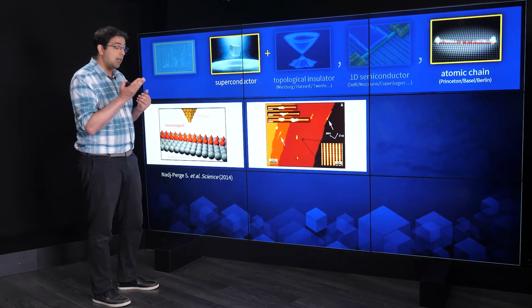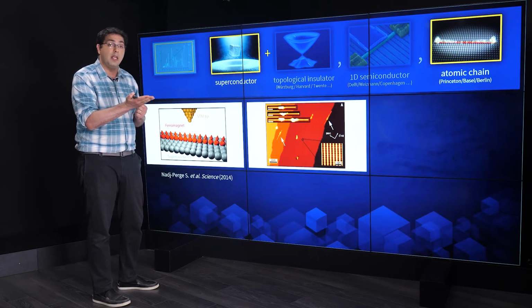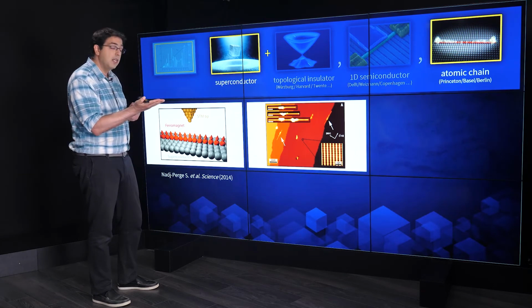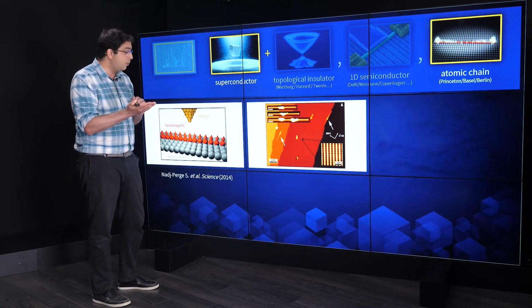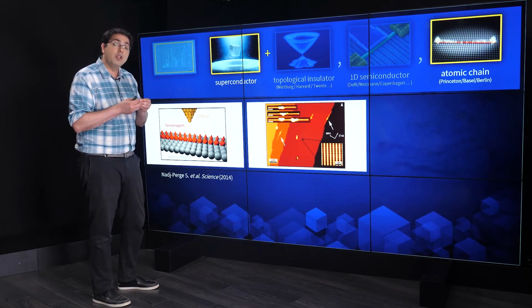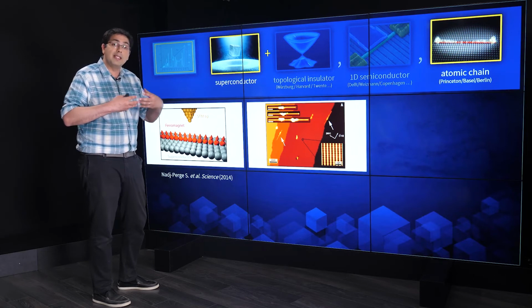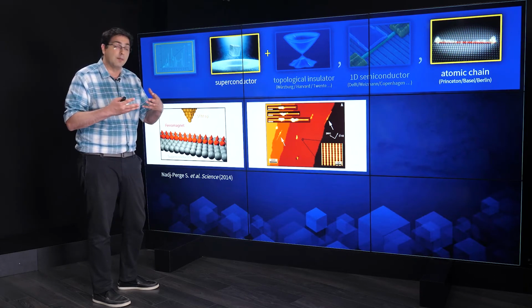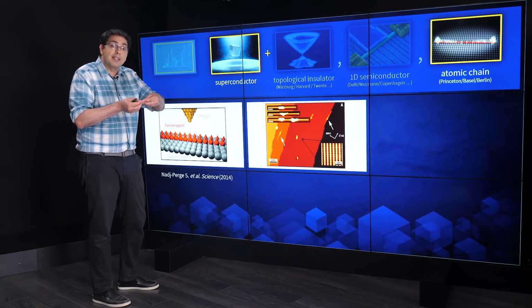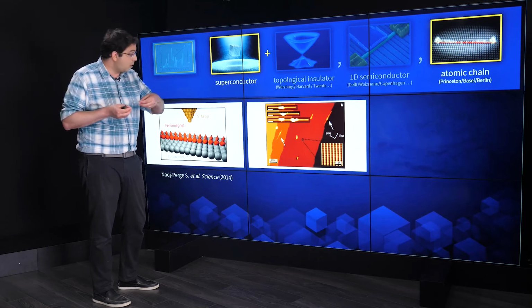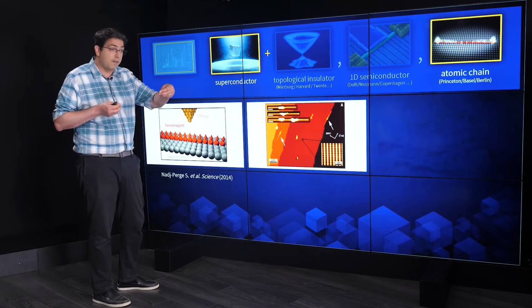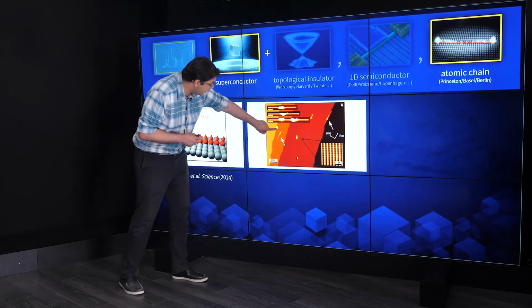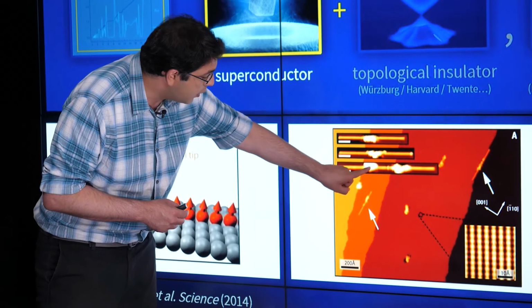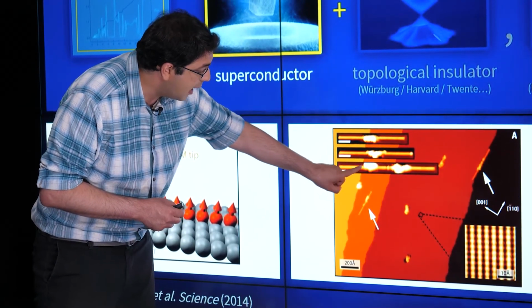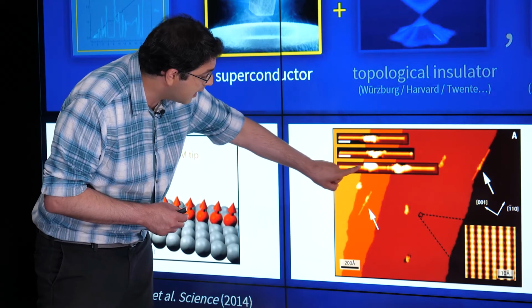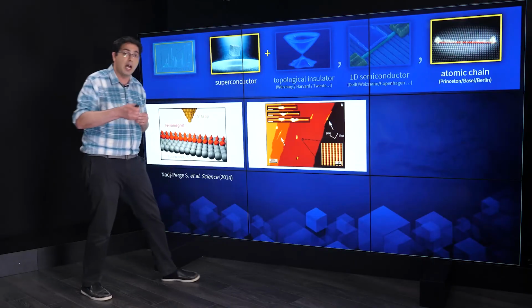So you basically take this substrate of lead, and then you evaporate iron on top of it, and then you anneal. When you anneal, you are increasing the mobility of the iron atoms on top of the substrate, and then they basically self-assemble as a line, okay? A line of atoms, which is what you see here. So you can see here, this is the place where the iron was evaporated, and then you have this self-assembled line of atoms coming out of it.